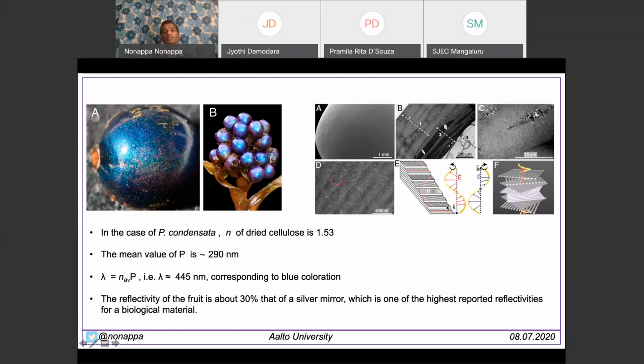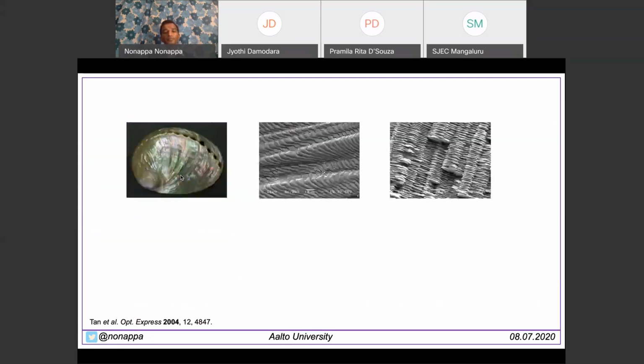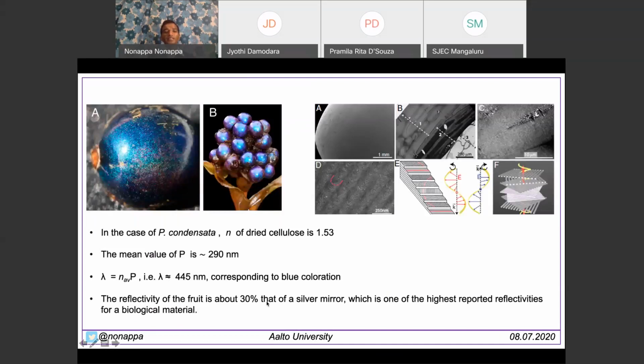And in this case, the pitch length P is about 290 nanometer. Now there's an equation where you can substitute this value and you get the wavelength around 450 nanometer. That 450 nanometer corresponds to the same color in the visible spectrum. So this is very interesting because it's a high reflectivity, and it's a record. There's no other biological molecule that shows so much reflectivity.